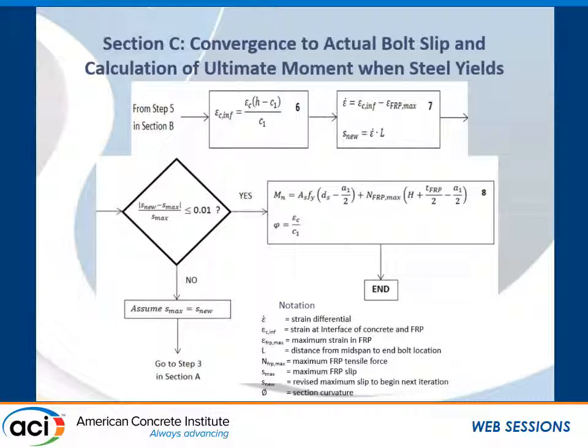Now, we developed a spreadsheet to complete the iteration process for the section analysis. The analysis method is not constrained by type of fastener, nor by the linear slip assumption that we used in the modeling that we did. The spreadsheet can be easily adapted to incorporate a different bearing slip model or slip pattern. The spreadsheet is also capable of analyzing cases in which failure occurs by FRP rupture, by anchor bolt bearing, or by concrete crushing prior to steel yield.